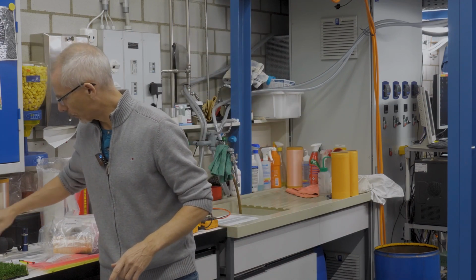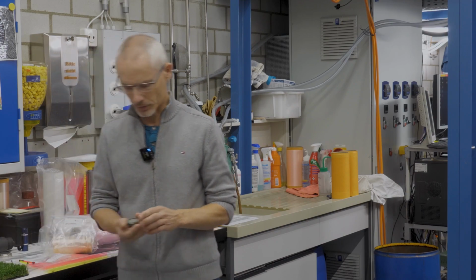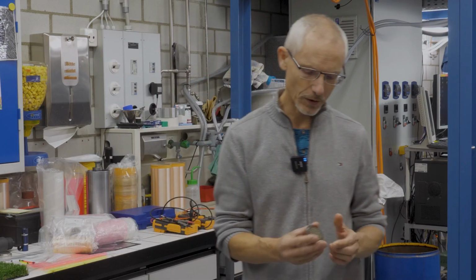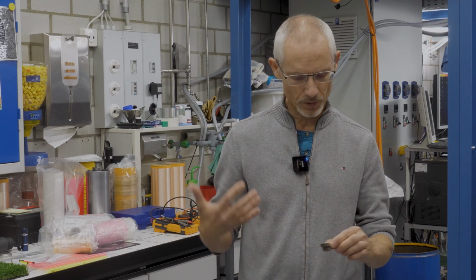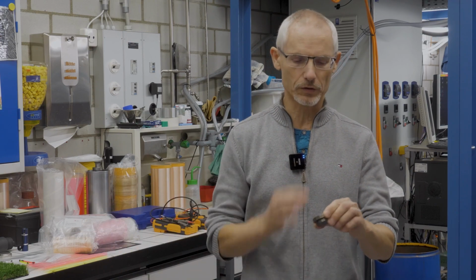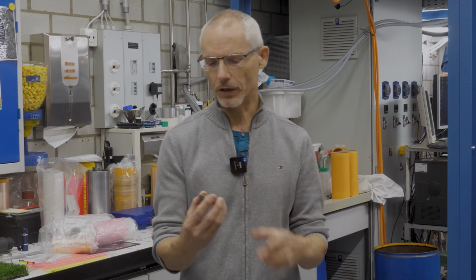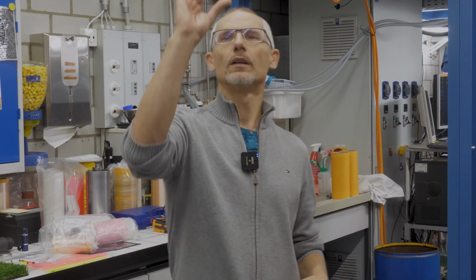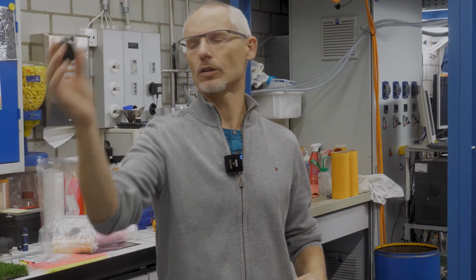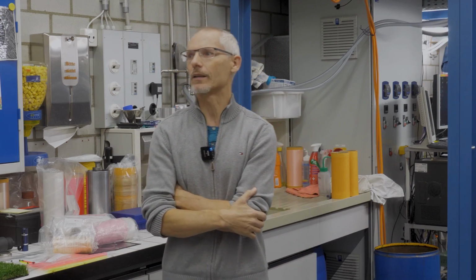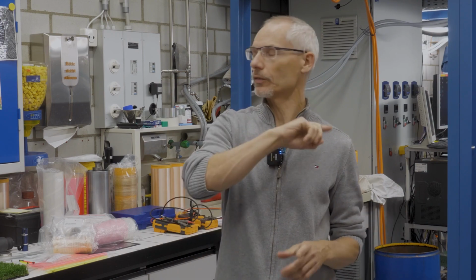Then we have the molten polymer, and we can press it through a so-called spinneret, which in that case is just one polymer, coming from one extruder, which we finally press through such a spinneret. And here we have 48 filaments, and you can look through, and then you see, when you look against the light, you can see very, very fine holes. That will press the polymer melt through. And then you have to solidify the melt. It becomes hard again, and then we process it further, which I will tell you later.